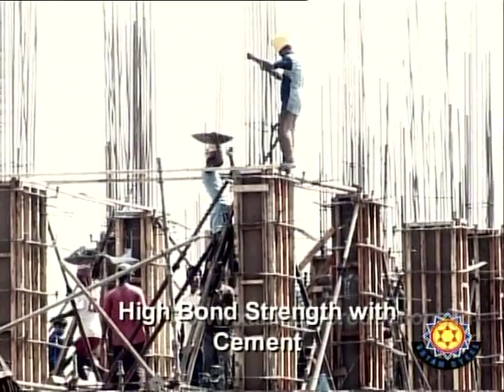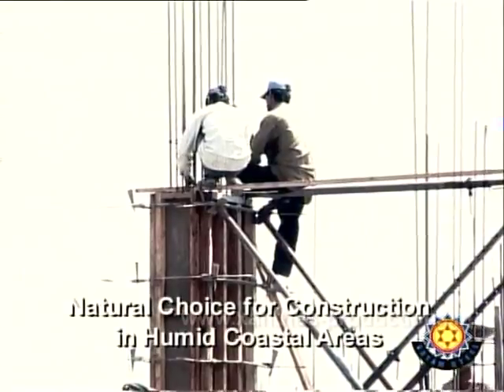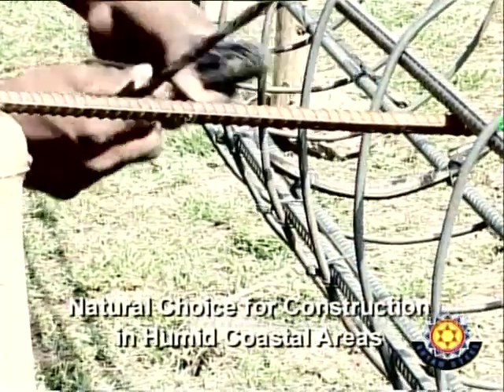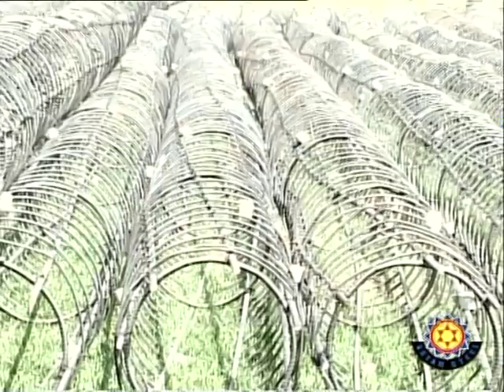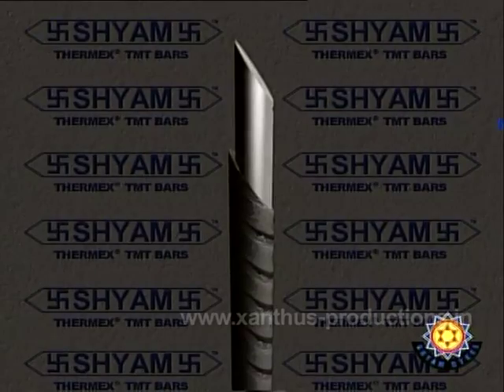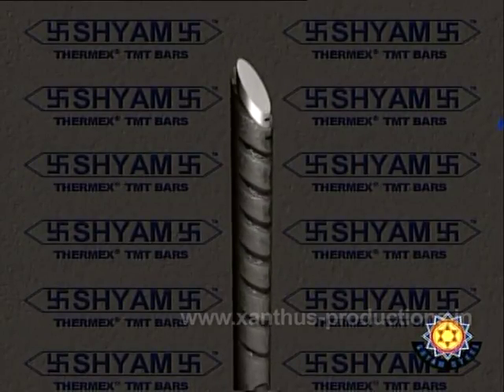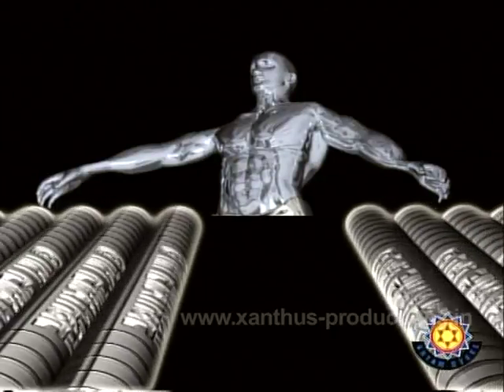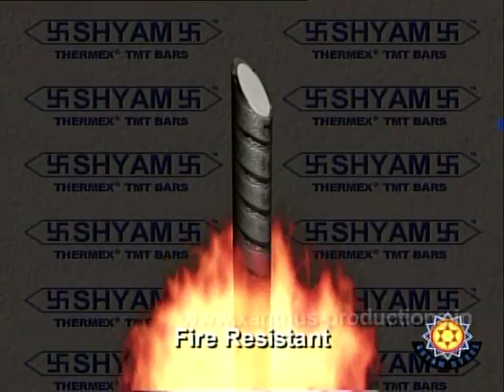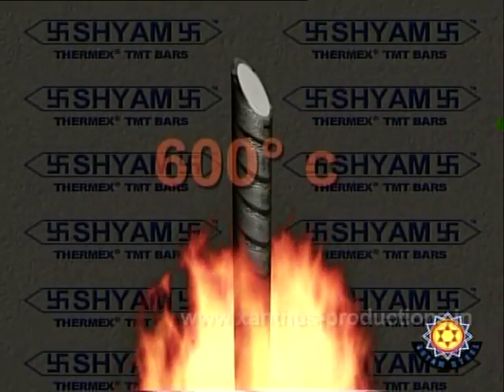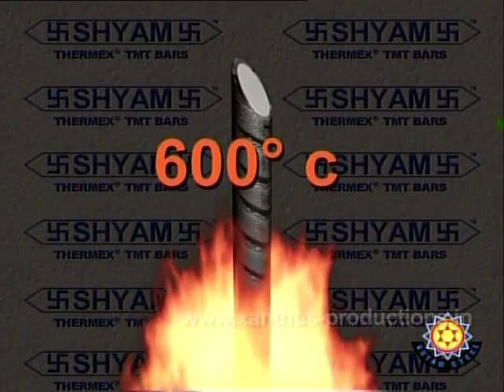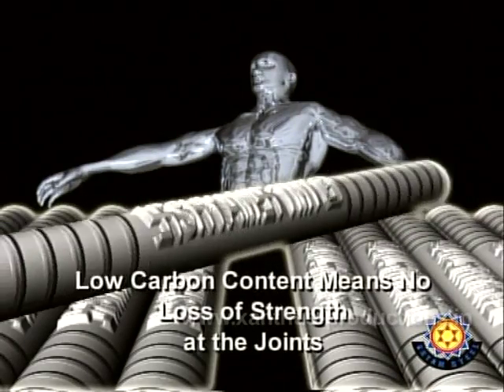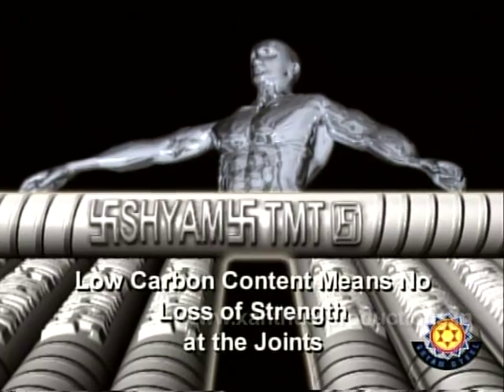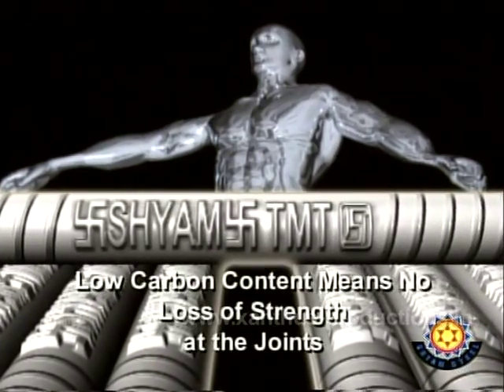Shyam Thermex TMT bars are the natural choice for construction in humid coastal areas, as the impregnable outer core makes the bars rust and corrosion resistant. Shyam Thermex TMT bars are also safe in the case of fire and can retain their strength at temperatures as high as 600 degrees centigrade. The low carbon content makes the bars easier to weld with no loss of strength at the joints.